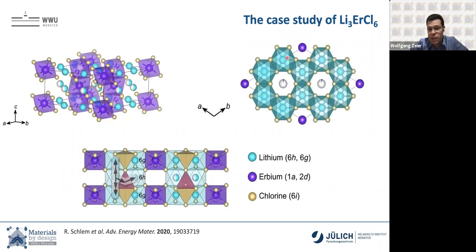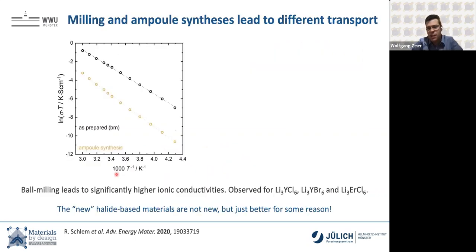The lithium sits somewhere in the middle, and the somewhere in the middle is forming a honeycomb lattice of octahedra. And so you can, in principle, have good diffusion in the AB plane, and in the Z direction there can also be good diffusion. But this doesn't really explain why there's this difference in ionic transport.